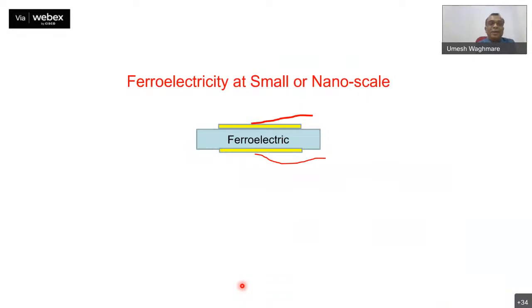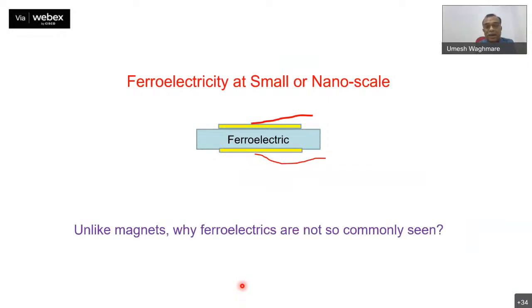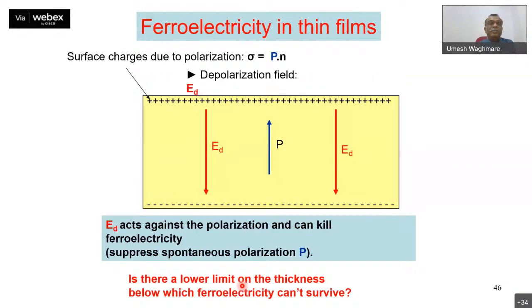Ferroelectricity, unlike magnets, is very sensitive to surfaces, and hence we don't see it in day-to-day life. And at nanoscale, it becomes even more interesting because this electric polarization generates these monopoles. In magnets, this is not so simple. Magnets don't have magnetic monopoles, whereas here the polarization generates surface charges, and that creates an opposite electric field, which can suppress the dipole itself.